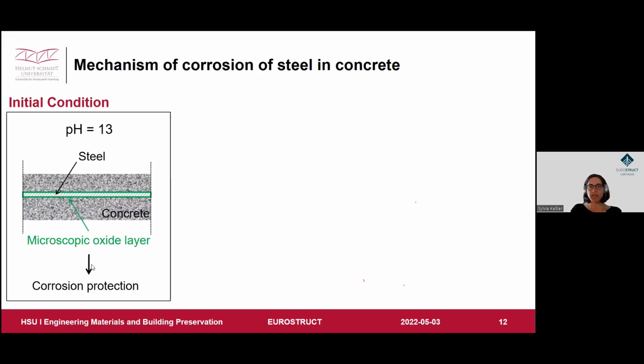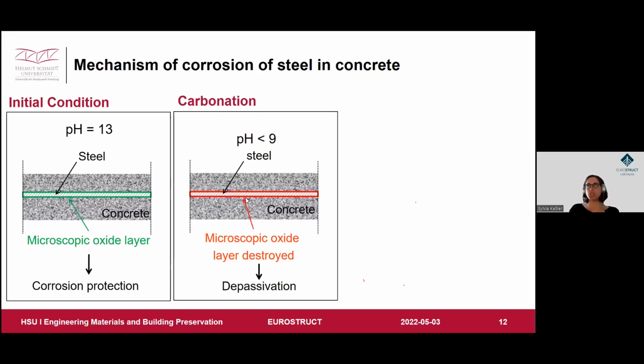Now we have two mechanisms, which we already heard about from the exposure classes. We have the carbonation, which leads to the process that the alkalinity gets lost, and the microscopic oxide layer, which normally prevents corrosion, dissolves. And so we have a depassivation. So the steel is able to corrode, which does not mean that the steel will corrode.